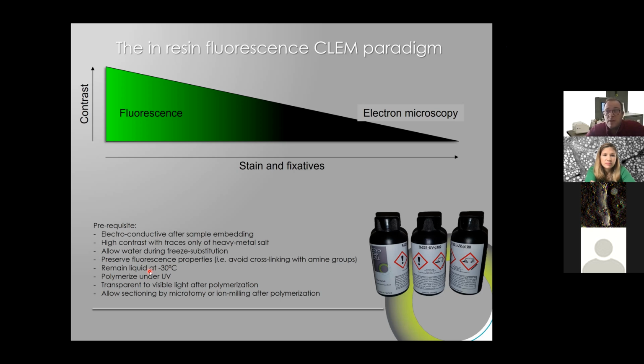The first idea was it should remain liquid at -30 degrees, because we wanted to take inspiration from the Lowicryl that is to us the gold standard, and I've used it personally mostly. So I like the Lowicryl for its ease of use. And so having something liquid at -30 degrees was something interesting. It should polymerize under UV because warming up the resin while you want to keep it at -30 degrees is kind of counterproductive. And I wanted to have a resin that could be stored in a chemical cabinet, not polymerizing because it's stored at 20 degrees. So the UV is convenient because it prevents an early degradation of the resin.